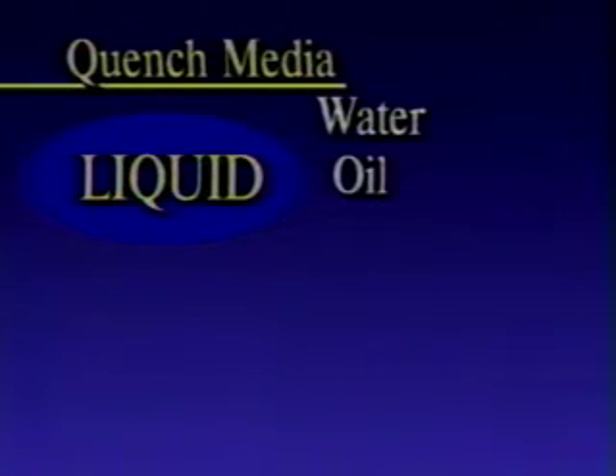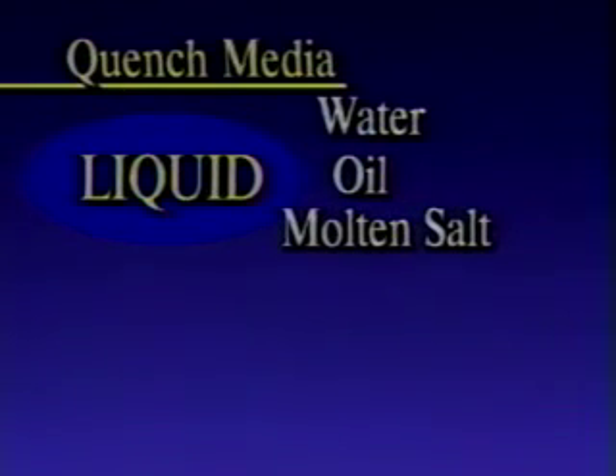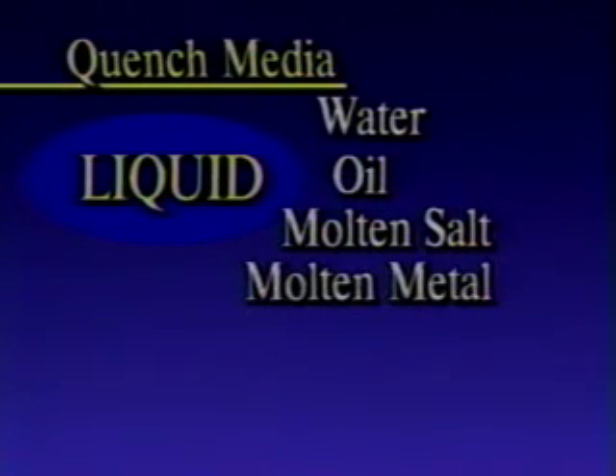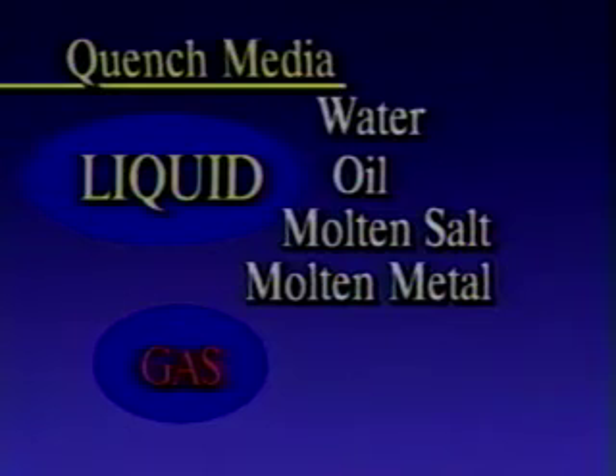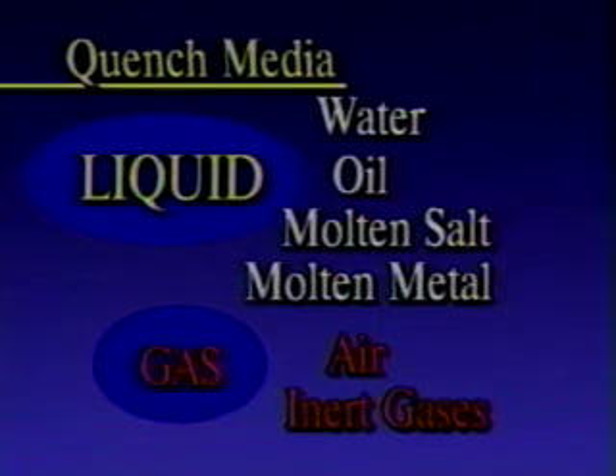Another type of liquid quenchant is oil. The oils used for quenching are specially formulated for various alloy compositions. Molten salt is also considered a liquid quenchant. Salts melt at elevated temperatures, and they make effective quenchants to hold alloys at specific temperatures. Finally, molten metals can also be used as quenchants. These are typically pure metals or alloys with low melting points. In addition to liquid quenchants, gases can also be used to quench. There are 2 types of gas media: air, which is air right out of the atmosphere, and there are inert gases that can be used to quench, primarily argon and helium.